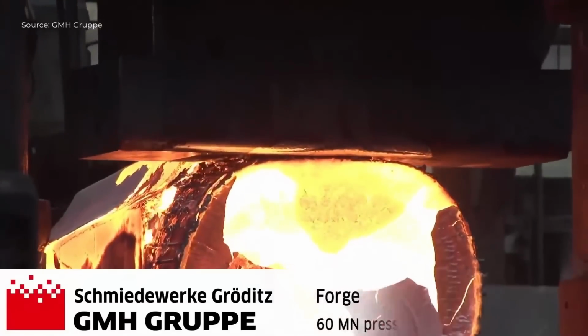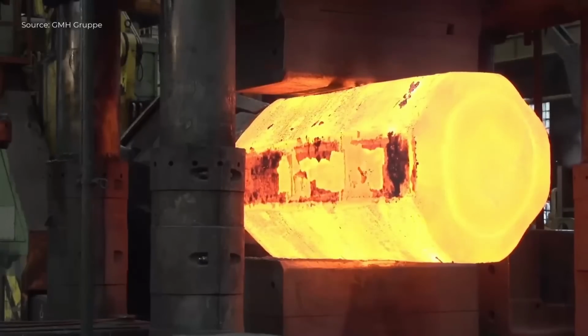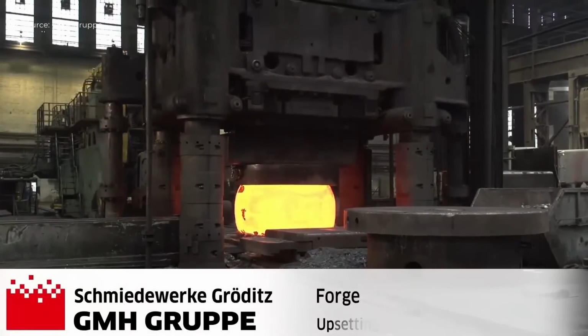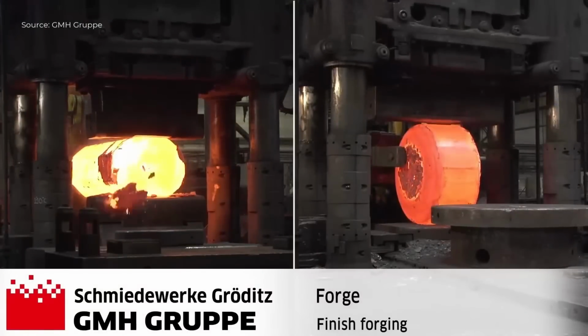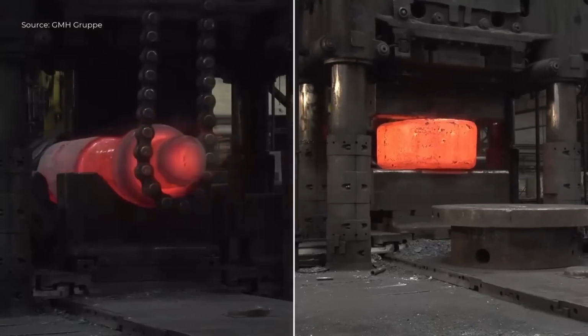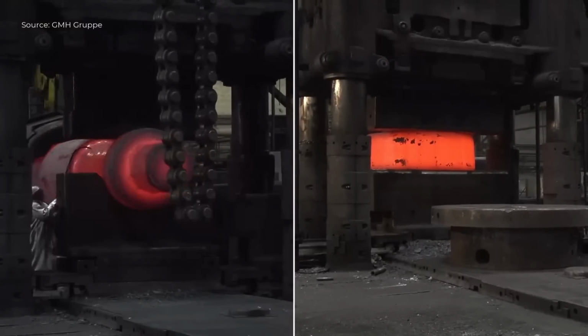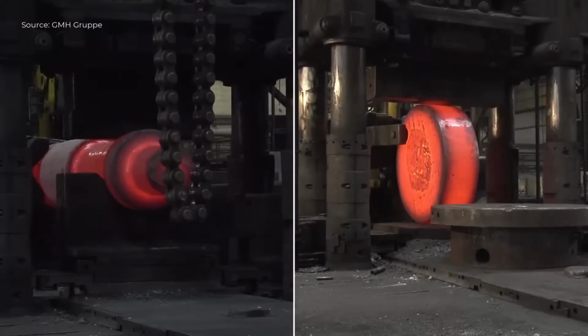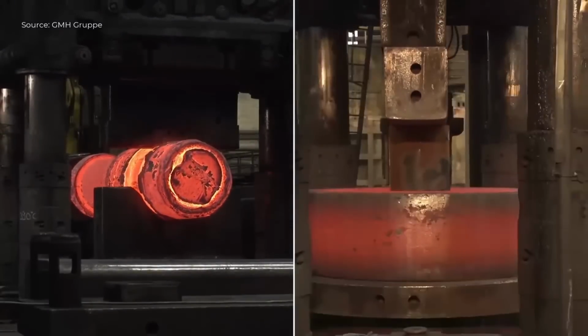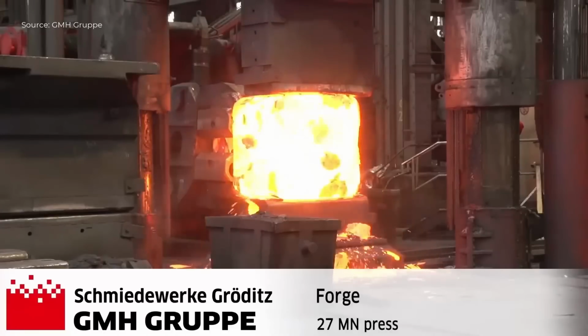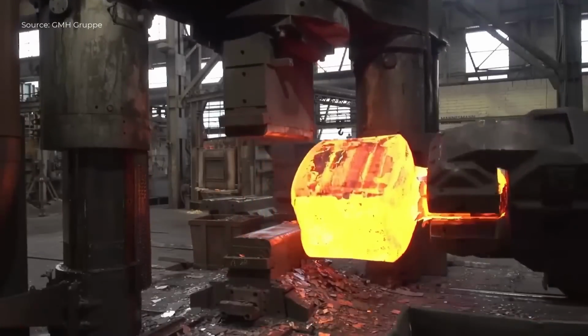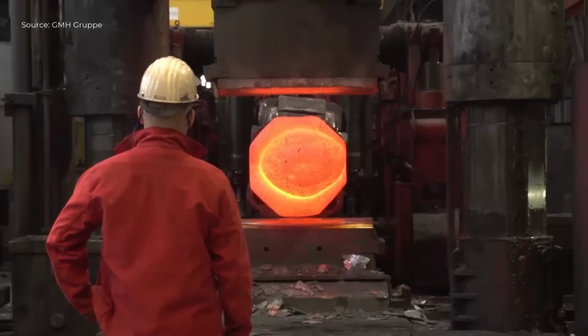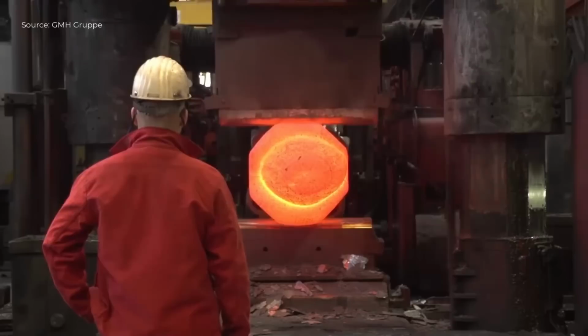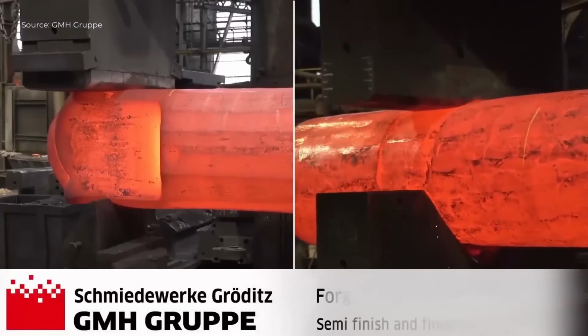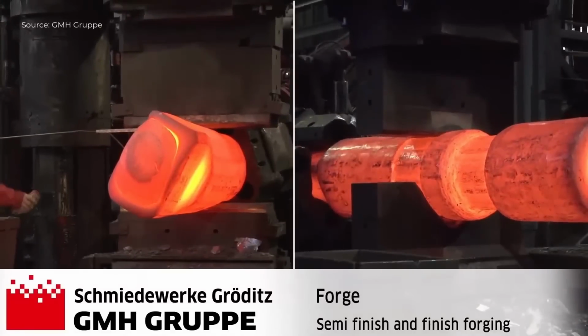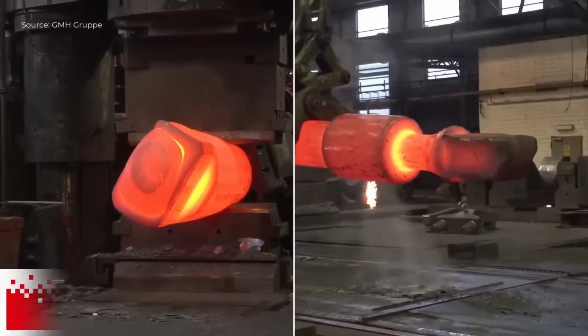Schmiedewerke Gröditz produces high-quality forged products for mechanical and plant engineering. The process begins with an electric arc furnace that melts up to 50 tons of liquid steel using 100% sorted scrap. After smelting, temperature and alloy adjustments are made in the ladle furnace, followed by casting into blocks suitable for forging. The largest ingot weighs up to 76 tons.